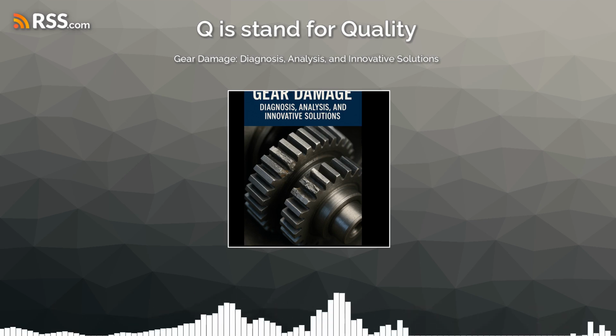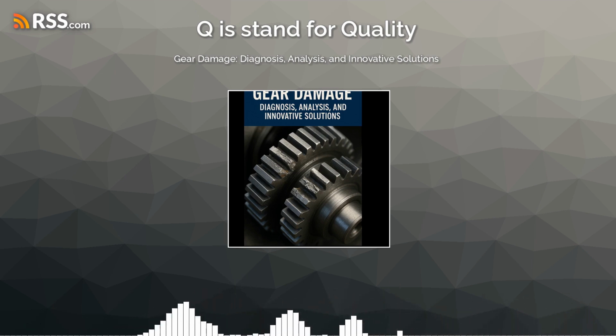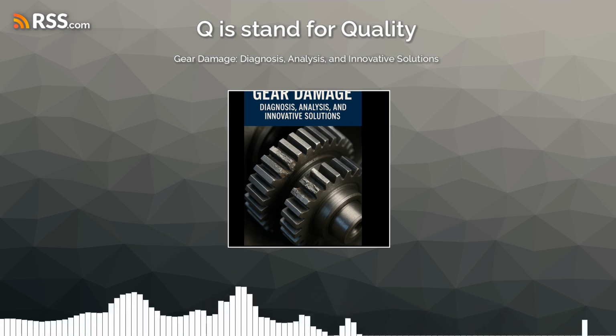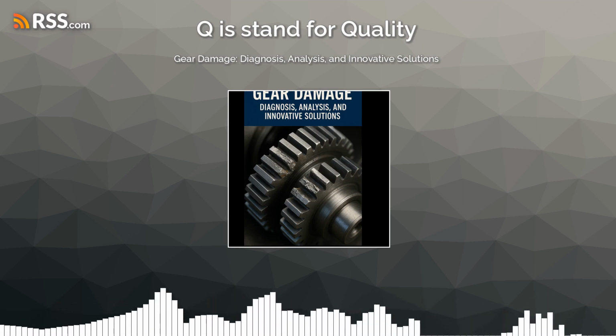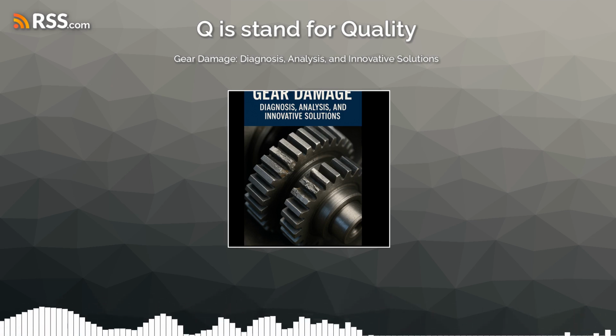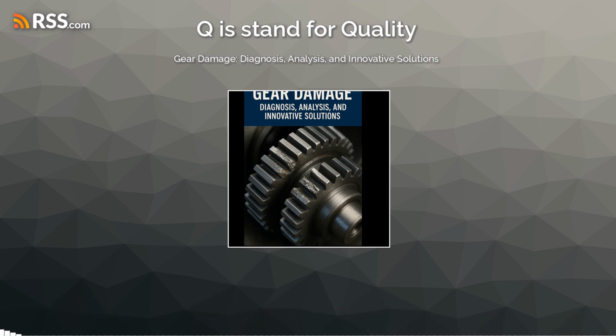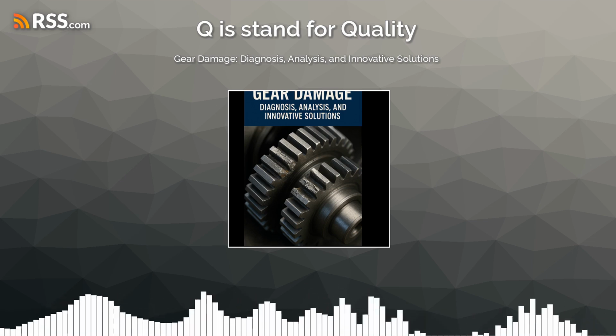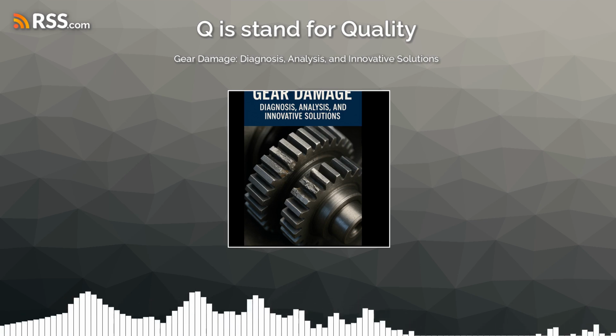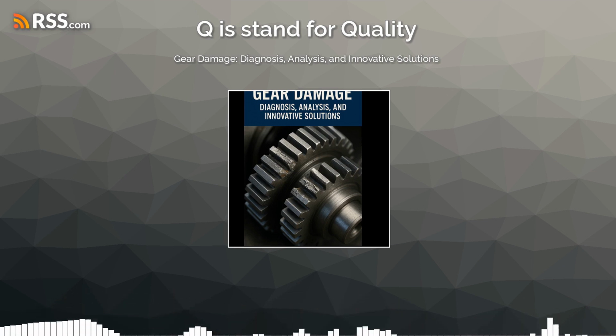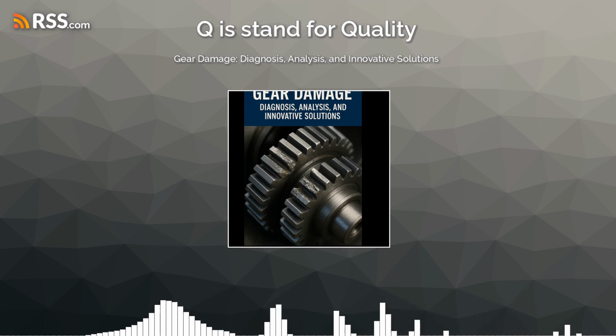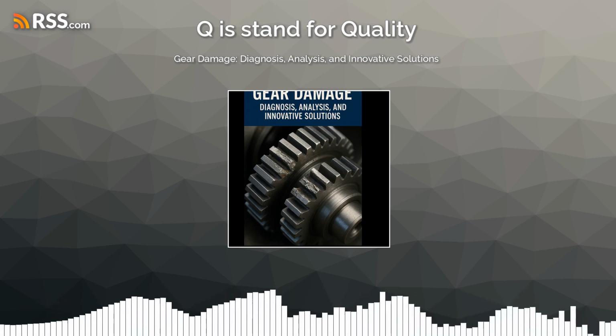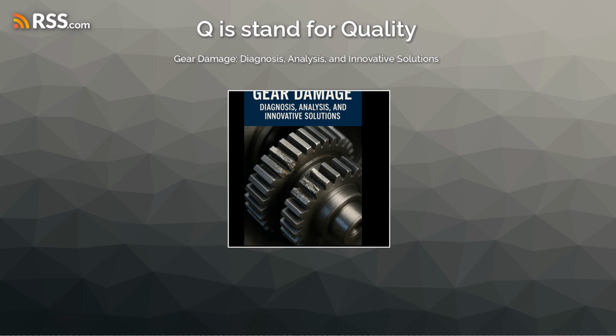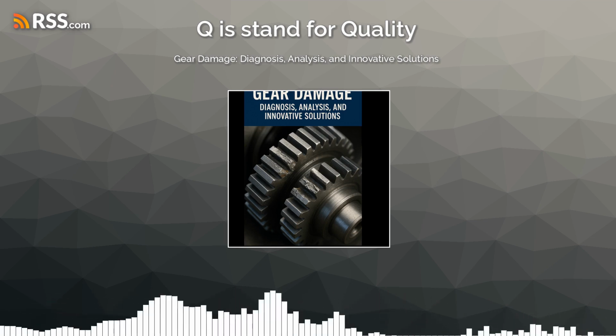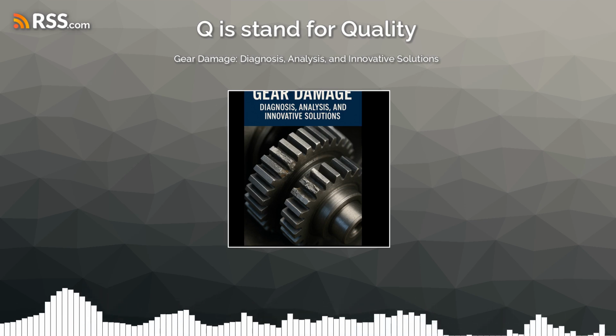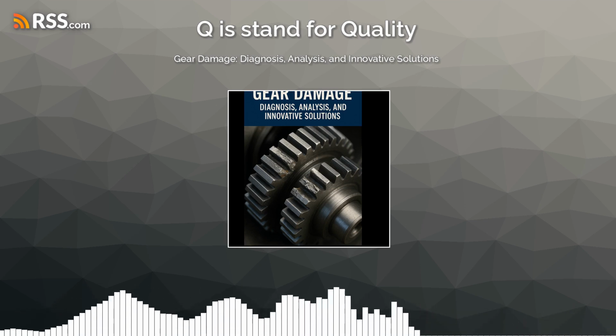And this complexity, it means the gear failure is often linked to other problems in the system, right? You can't just look at the gear alone. You've absolutely hit the nail on the head there. It's impossible to understand fracture just by looking at the gear in isolation. You need a system-level approach. A gear doesn't work alone. It's connected to shafts, bearings, the lubrication system. A bearing failing could cause shaft misalignment, which puts extra stress on the gear, leading to fracture. Ah, I see. So if you only looked at the broken gear, you might miss the real root cause, the failing bearing. You have to analyze the whole transmission system to truly understand why it failed and how to prevent it happening again, system-wide. It's seeing the whole picture.